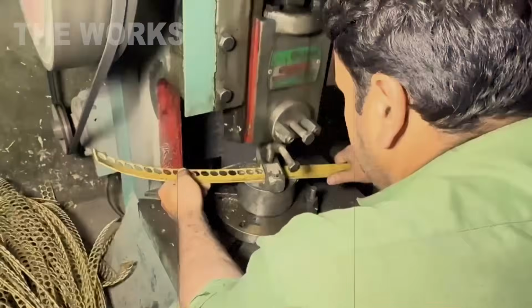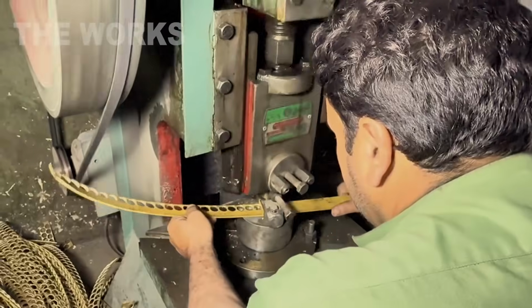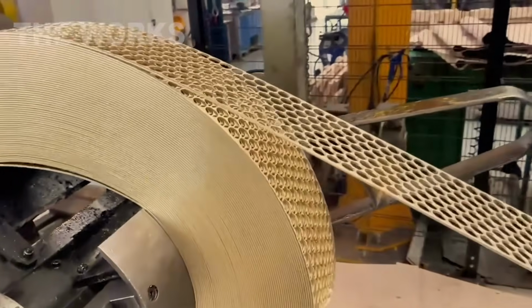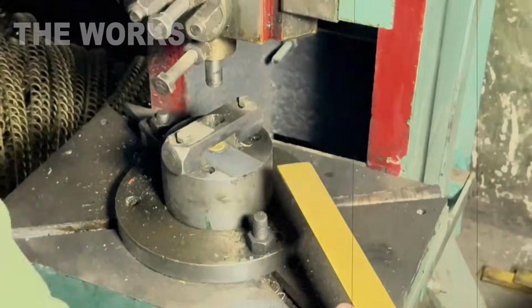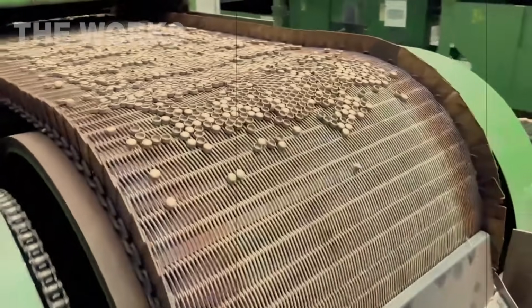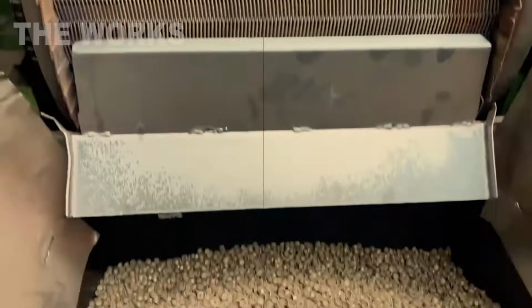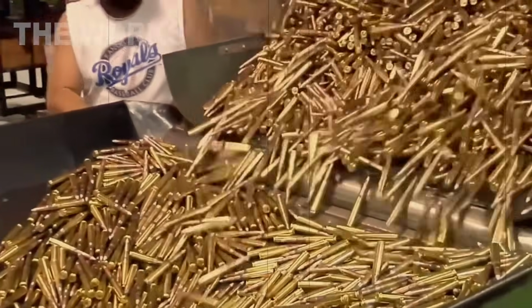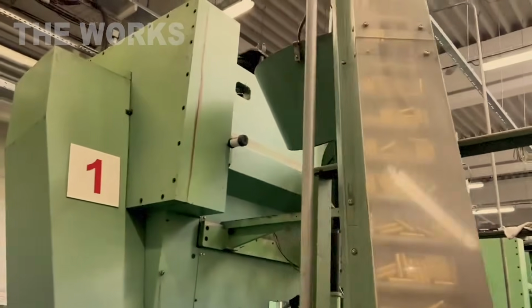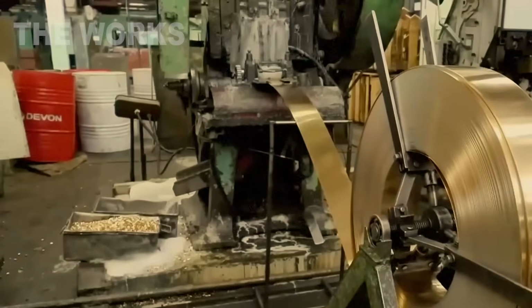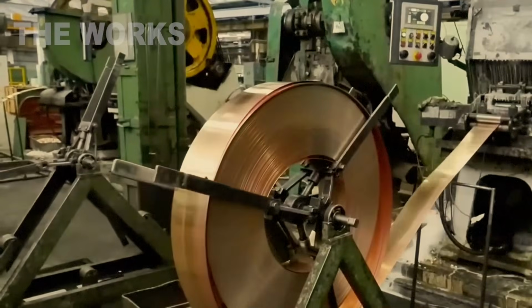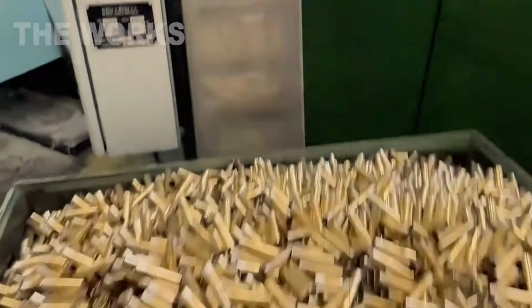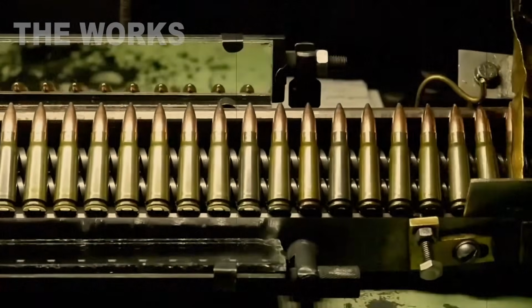Next, the brass sheet is fed into a press line, a high-speed stamping machine that cuts out discs with lightning precision, so-called blanks. Their diameter is roughly 19 millimeters. The press operates at up to 250 strikes per minute. The resulting discs are heated to 430 degrees, essential for the next deep drawing process. They're immersed in lubricant and fed into a hydraulic press, where under pressure of up to 100 tons, the disc is formed into a primary case. This process repeats several times, each time drawing the case slightly longer and thinner.